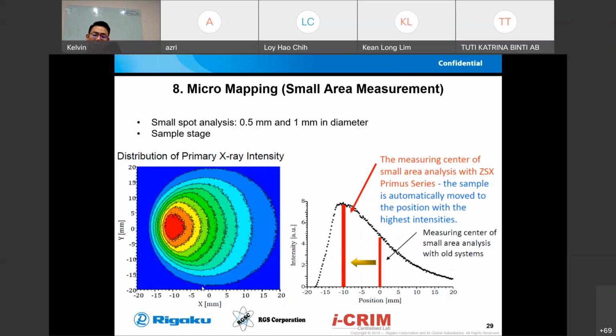One thing is that just now we also mentioned the X-ray intensity. The highest intensity is not at the middle part; it is actually shifted to the left-hand side. So when you are doing this type of measurement, the hardware of the Primus 4 will automatically measure at the part having the highest intensity. Then you can increase the measurement intensity of the sample.